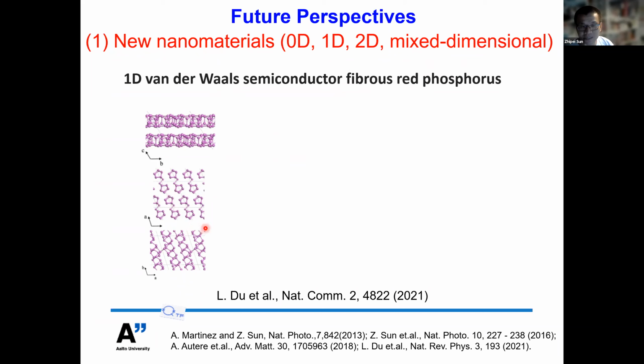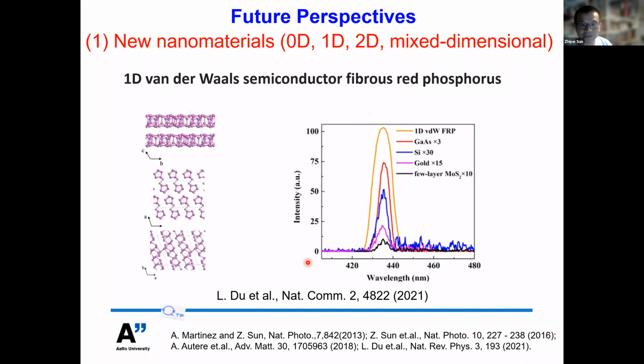For example, this is an example of our recent published paper. We found that the one-dimensional van der Waals semiconductor red phosphorus has a very large chi-3 response, much stronger compared with monolayer MoS2 and also other well-known chi-3 materials.